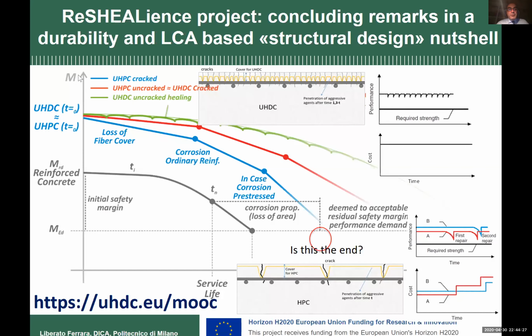If you plot structural performance over time for reinforced concrete, you get a curve like the gray one. You start with a certain performance, then have a slow decay, but at a certain point carbonation or chloride-induced corrosion begins, and performance starts decreasing very fast. When performance reaches a level too close to the demand, that's the end of service life. Using higher performance materials, we can increase performance at time zero and also govern the degradation over time.